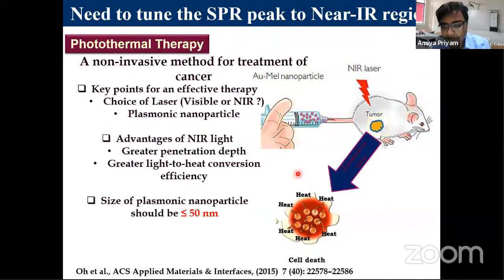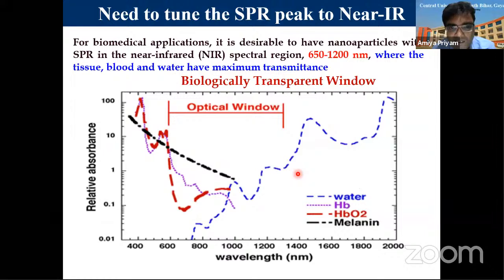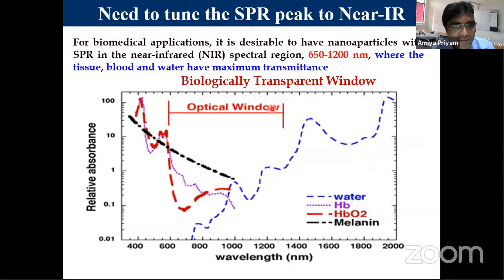So it has been found by analysis that there is an optical window from 650 to 1200 nanometers, which is transparent from the biological point of view, that is, none of the cell organelles or biological components absorb in this region. They have negligible absorption, so it can be said to be transparent in this region. This is the optical window, the spectral window that we need to utilize for this kind of light-induced therapies, light-induced diagnosis, if we want to make them non-invasive.